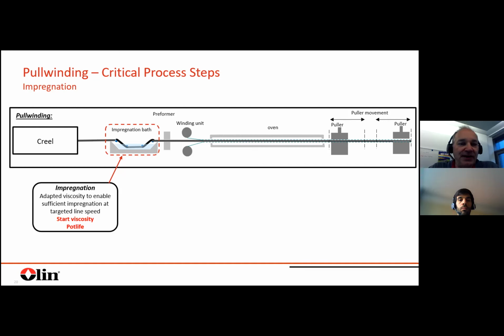So key criteria here, it's for sure we have to ensure that there is a sufficient and good impregnation at targeted line speed. So that means for high productive processes like the rebar production, we're more discussing 5, 10, maybe faster. So that means that here the requirements on the impregnation are different than in comparison to pultrusion, where we're more discussing a range up to 1 meter per minute and maybe now going also slightly higher, but it's a completely different range.